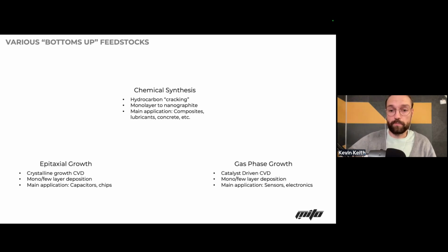Then you have gas phase growth, which is a catalyst driven CVD. So think you have a gas that is carbon rich within a certain machine that has a silicon wafer. You introduce a catalyst, it cracks that carbon apart, the carbon snaps to that silicon wafer, and out comes waste. You can have mono and few layer deposition for this. Main application: sensors, electronics. Some really amazing sensors can be made with this gas phase growth method, because you're able to sense electron movement and have very, very, very sensitive sensors that has actually unlocked a lot of great potential.